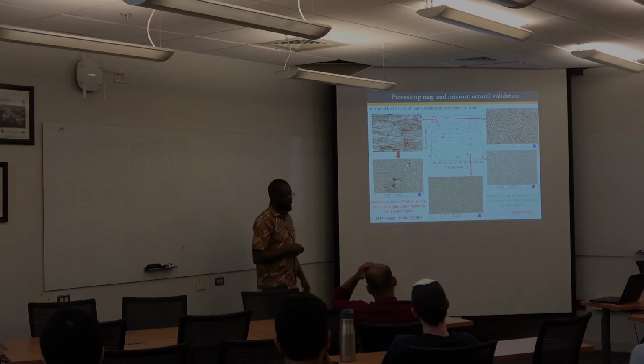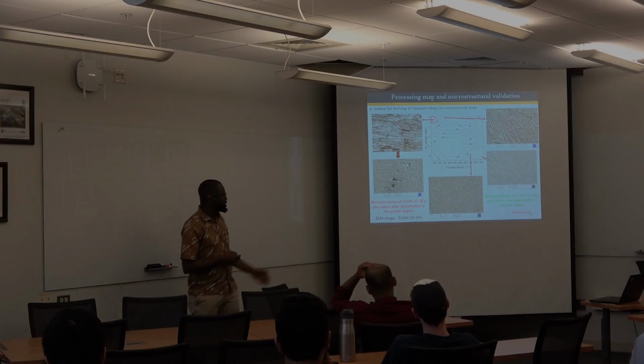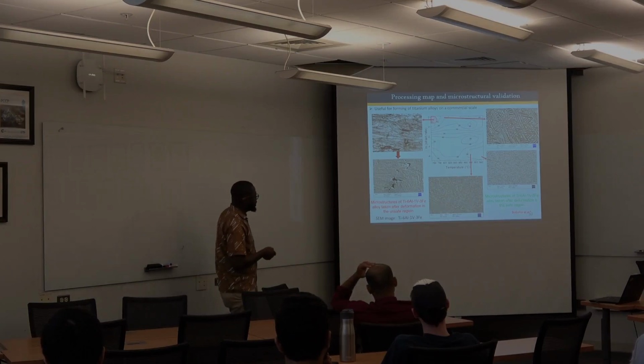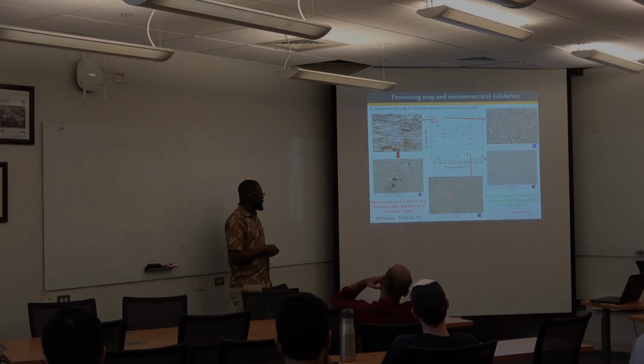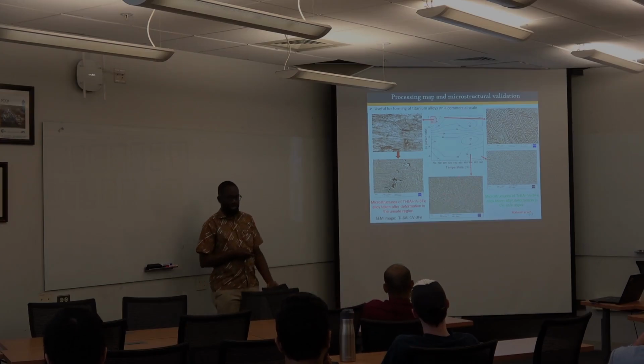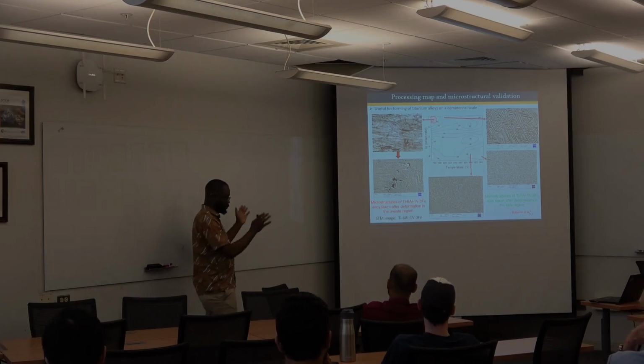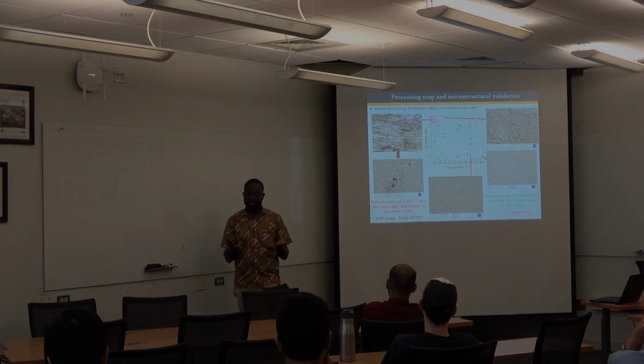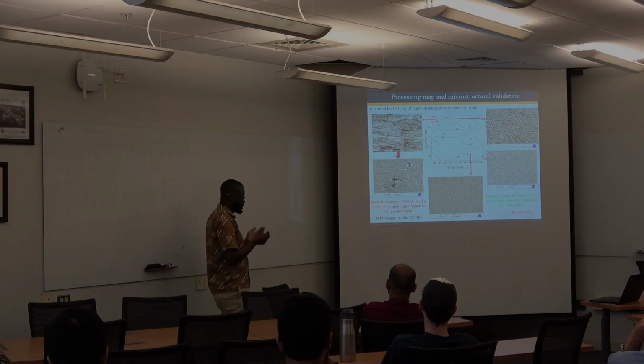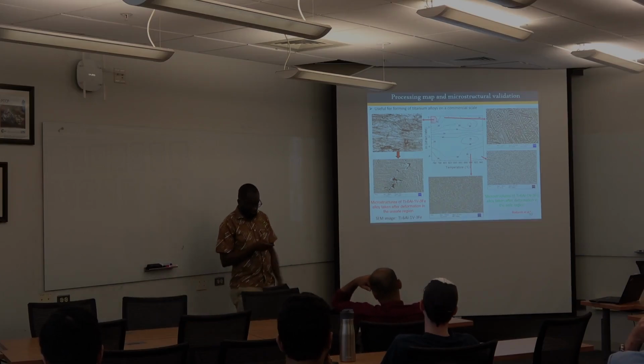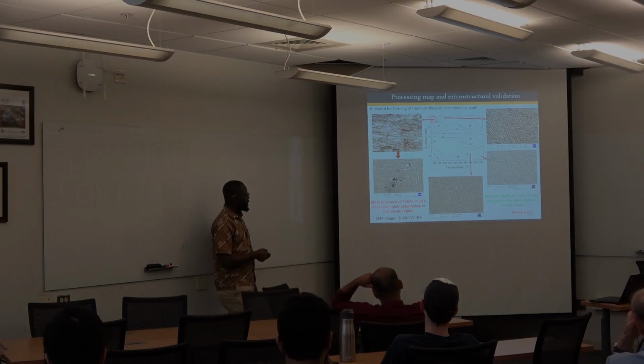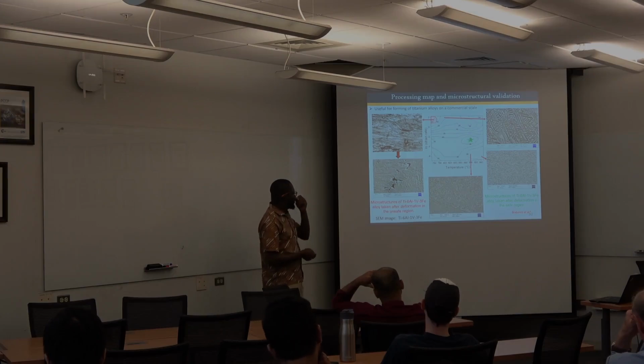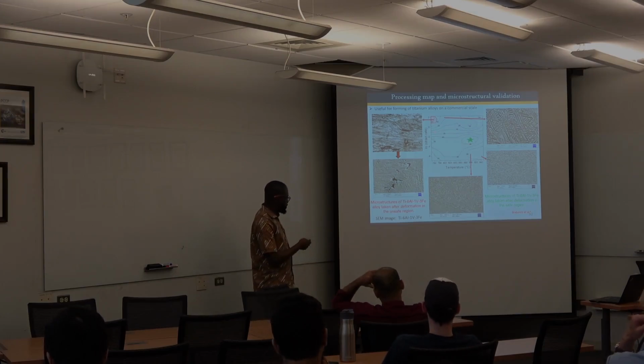But what I really want to show is that without following all the 4 steps that have been proposed for processing alpha-beta titanium alloys from as-cast to rod state, you can see that we are beginning to form some globules here at high temperature and, of course, at very slow strain rate. Okay, so the question is, we then need to compare: if you do the 4 processes or you do this, which one is cheaper? But the truth about it is, this is a shortcut to getting the globularized microstructure and not the full microstructure. So that region would be the optimum processing condition for the alloys in general. But now I am focusing on this particular alloy anyway.